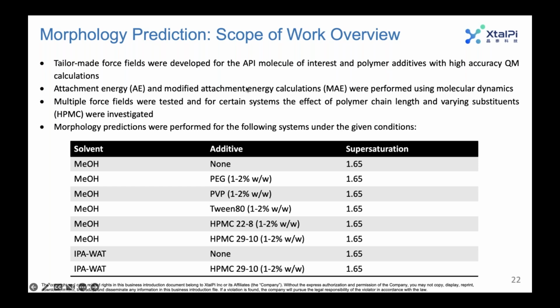We used the modified attachment energy method with molecular dynamics. That was the workhorse of this study. We developed many different force fields to compare how they performed on the system. So we've developed a way to not only parameterize those, but also evaluate their performance. We also looked at the effect of polymer chain lengths and also the effect of varying substituents for the case of HPMC. And we performed morphology predictions under the following experimental conditions.